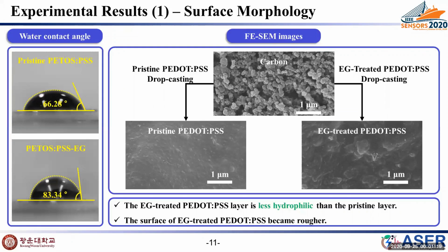Now, I'm going to show the experimental results from this slide. The ethylene glycol treated PEDOT:PSS film showed a slightly larger water contact angle of about 83 degrees than the pure film. It means the treated film is less hydrophilic than the pristine film. And from FESEM images, it was found that pure PEDOT:PSS on the carbon electrode is thick and its surface is smooth. On the other hand, the surface of the ethylene glycol treated PEDOT:PSS became rough. From this, we can predict that the surface area would have increased slightly.